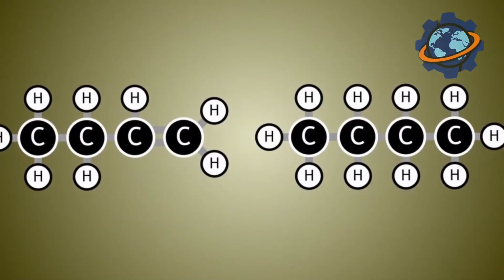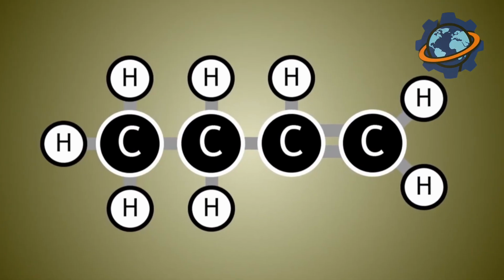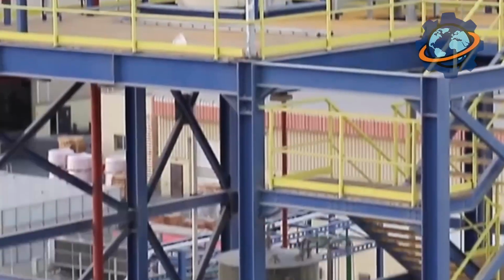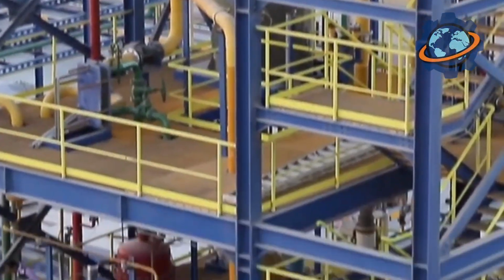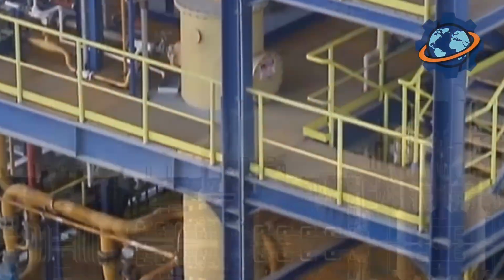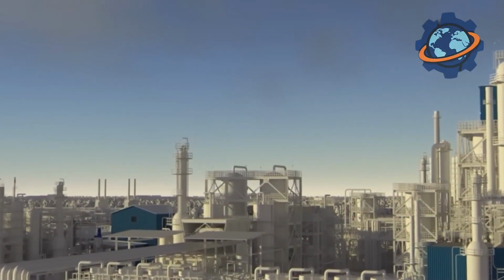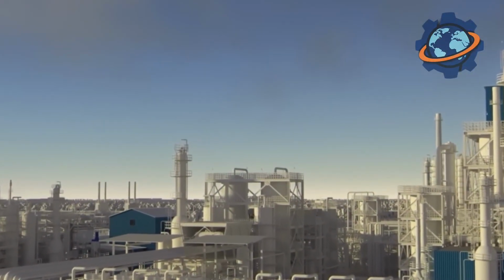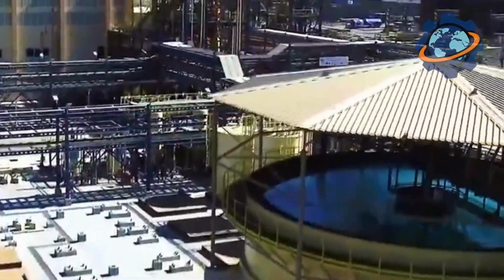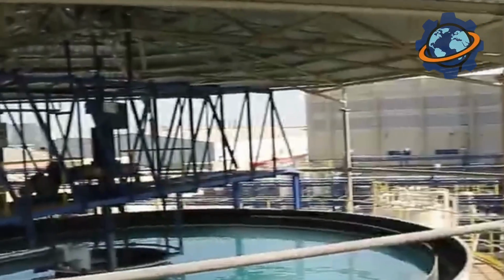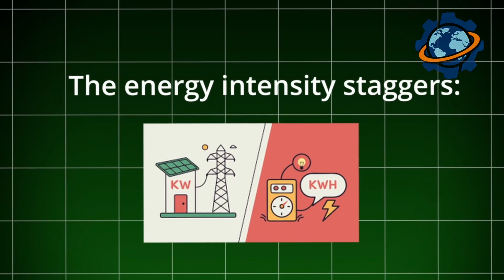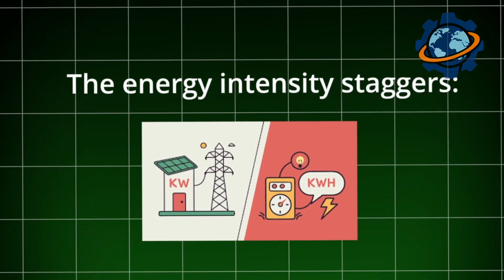After 10 days, workers crane lift finished cathodes, now coated with 400-pound nickel deposits from the baths. Mechanical strippers peel nickel from starter sheets like removing wallpaper. These pure nickel sheets, called cathodes, get melted into pellets for battery manufacturers, or alloyed with chromium and iron for stainless steel. The energy intensity staggers.